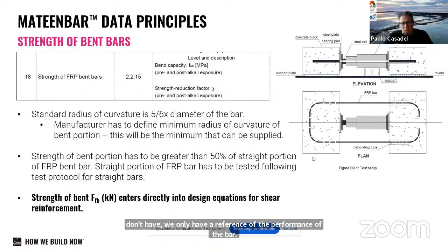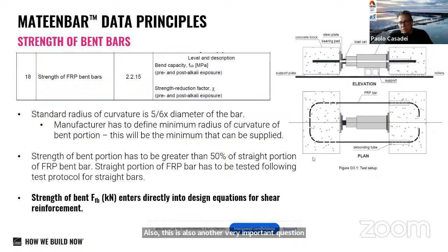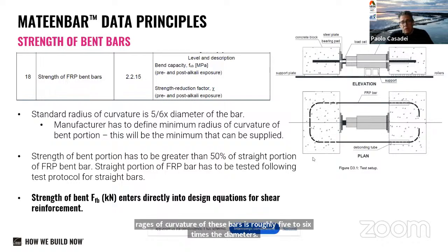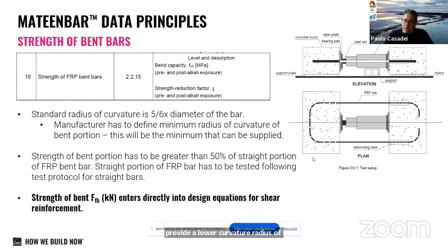Also, this is another very important question regarding bent bars. Like we said before, one limitation of this technology is that we cannot bend GFRP bars on site. GFRP bars have to be manufactured separately in production. Usually the radius of curvature of these bars is roughly 5 to 6 times the diameter. Clearly the manufacturer is allowed to provide a lower curvature radius for their bar as long as the minimum mechanical properties that are listed in the code meet the specification.